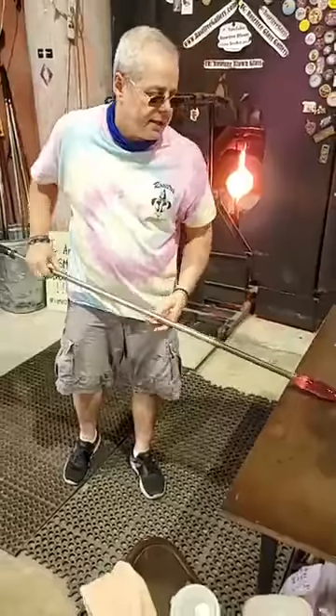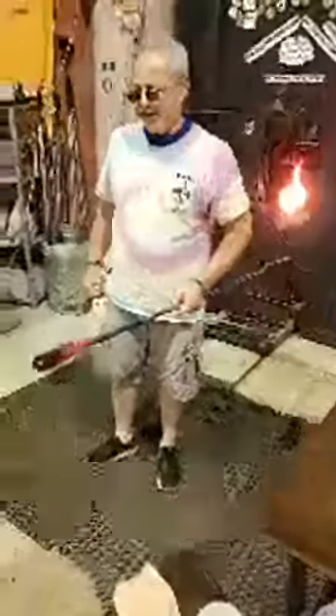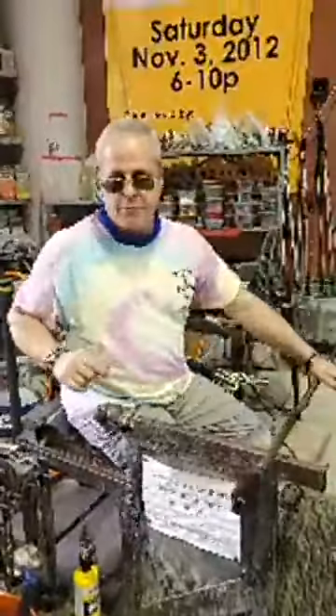Jerry Lynn is here — hello, Jerry Lynn. And my awesome Aunt Tracy is actually watching — hey, Tracy! So we're going to let this cool off. By doing that we'll be able to get the next layer on top, and this will support that next layer. If we went in too hot, that next layer would heat this up and it would become really, really floppy. My indicator, as always, is inside the pipe — it's now kind of orange. It'll go through red, and then it'll kind of clear up, and that'll be my hint to go back in and get some more glass.